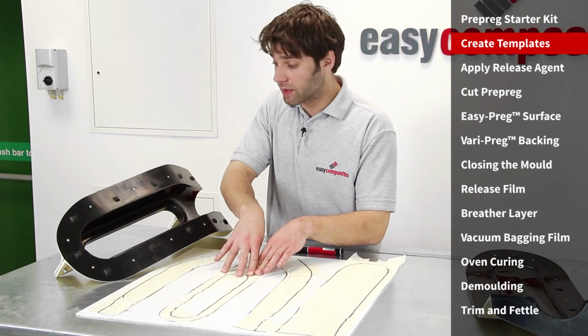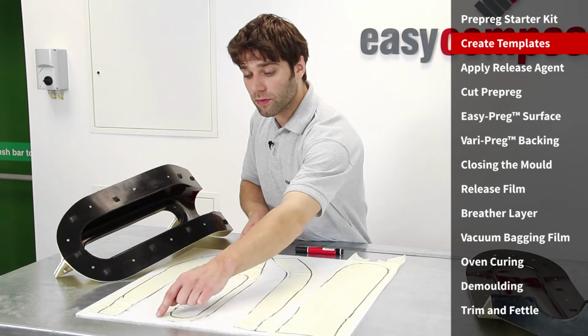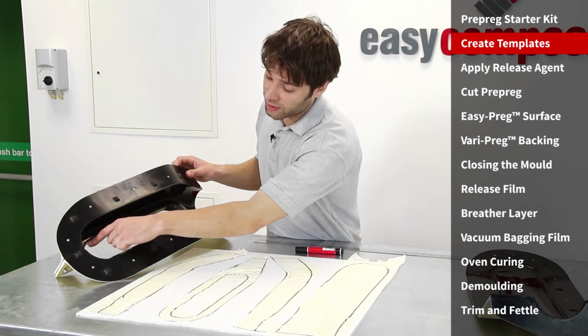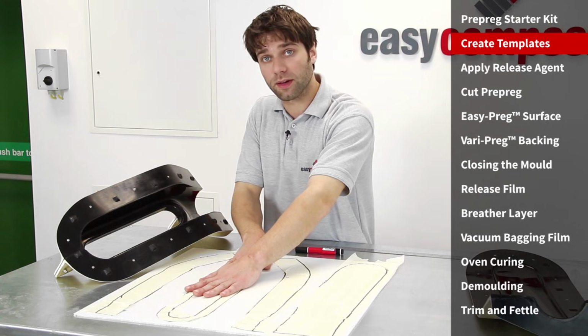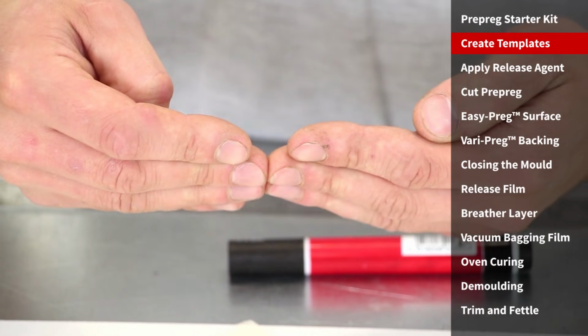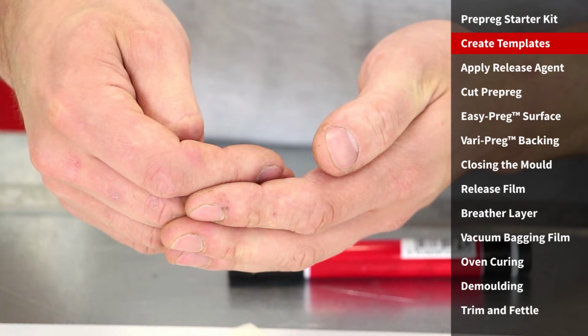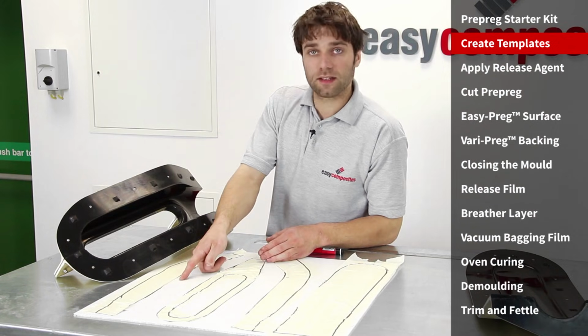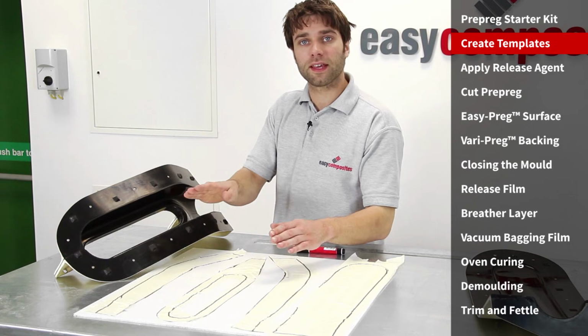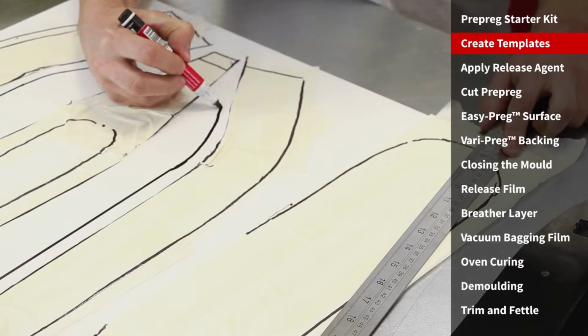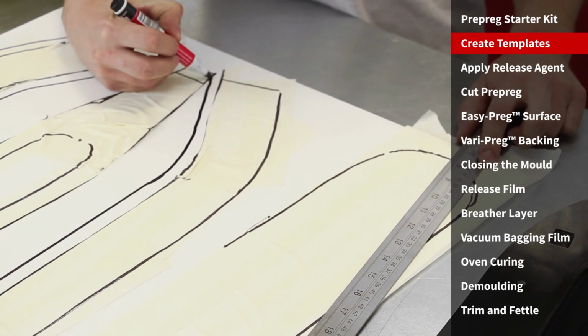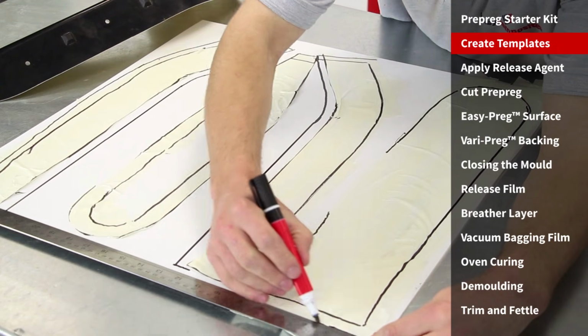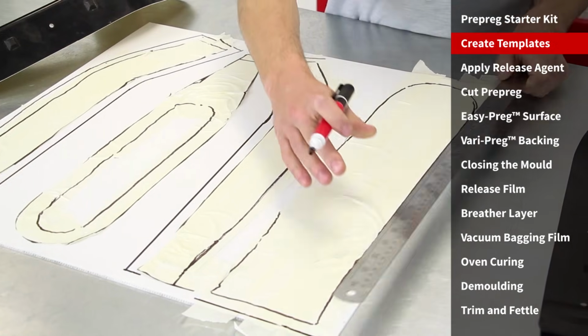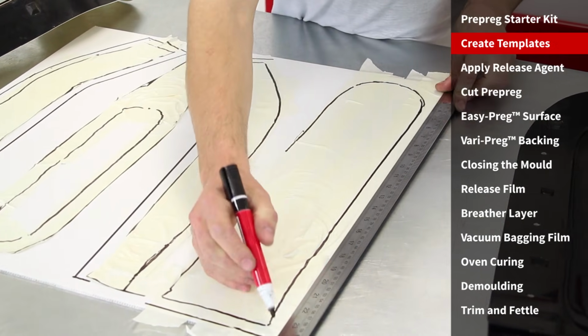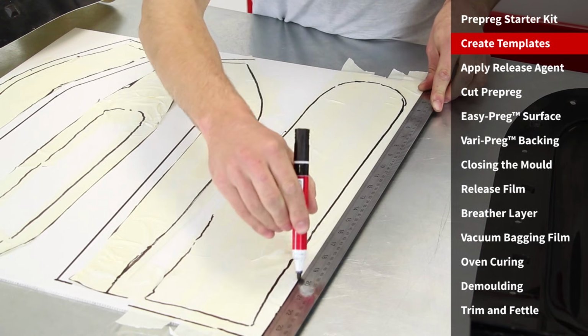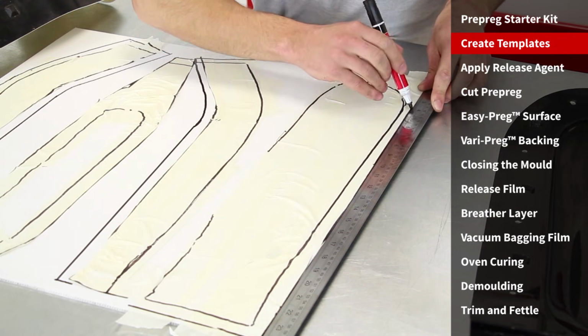This will be our first component into the mould, so we want this piece of material to be precisely cut to that line. So this won't get changed, it will be cut out at that size. However, where the join is, it's much better to have an overlap of material rather than a butt join. So we will extend the side panels here out by around about 10mm to give us that overlap. When we're looking at the top section, we'll be cutting this one slightly oversized just to give us an extra bit of tolerance, some margin for error when we're laying it up before precisely cutting it down to the seam on the mould.